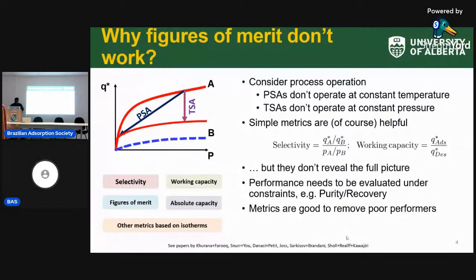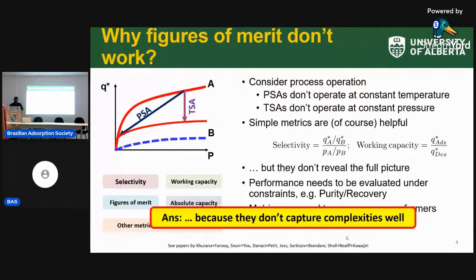The other reason why I believe metrics don't work is because from a process perspective, you're also trying to evaluate under constraints. I need to achieve a certain purity, I need to get a certain recovery. So these metrics don't give you that information unless you actually put them in practice. Right? So I can have two materials. One could give you 70% purity at a lower energy consumption. Maybe the other one gives you higher purity at a higher energy consumption. We cannot put them on the same plane. We have to keep something fixed, and typically they show up as constraints. So those have to be fixed in order to compare materials. Again, as I mentioned, metrics are, in my view, not the answer because they don't capture the complexities of a process very well. Now, why move to process-based screening?